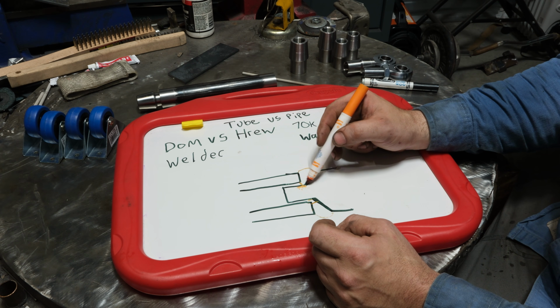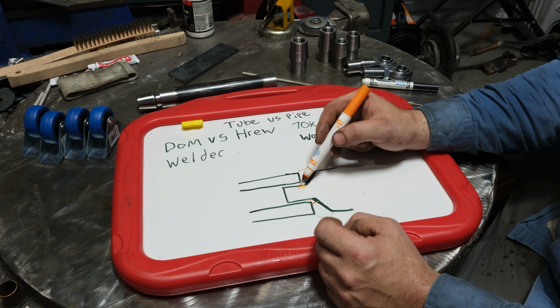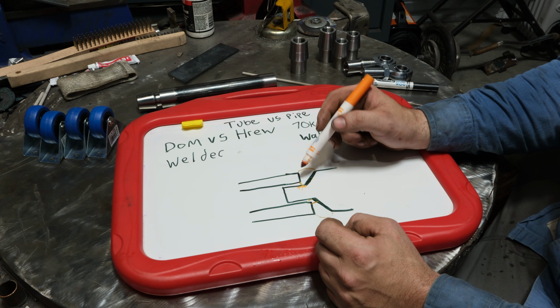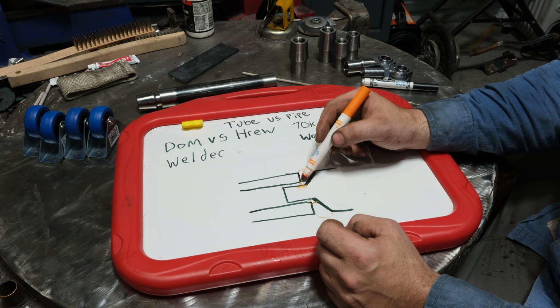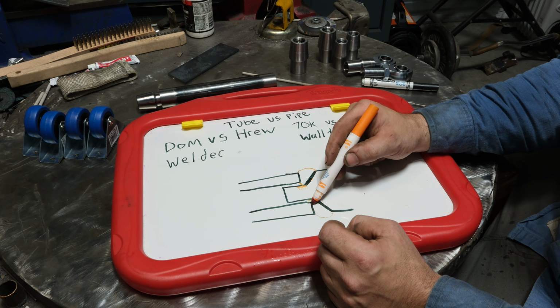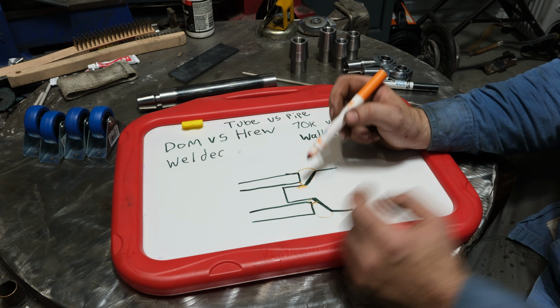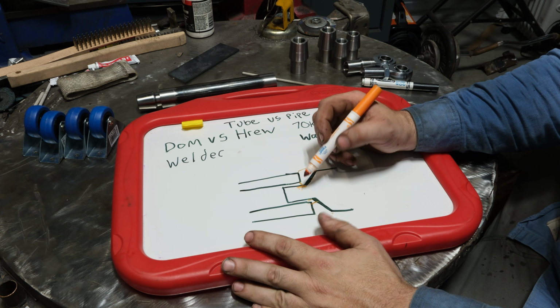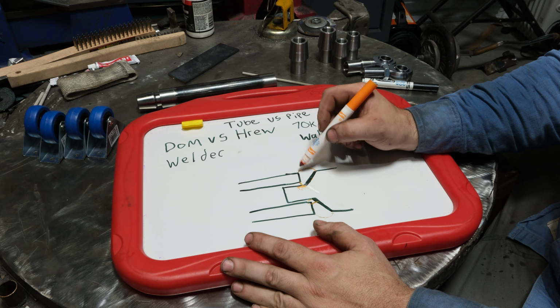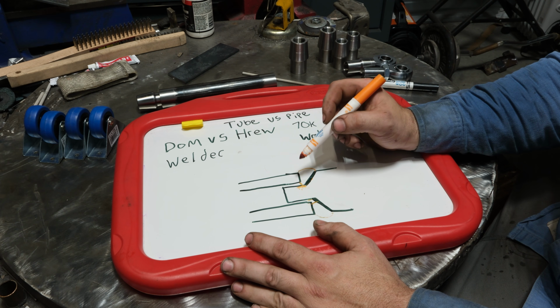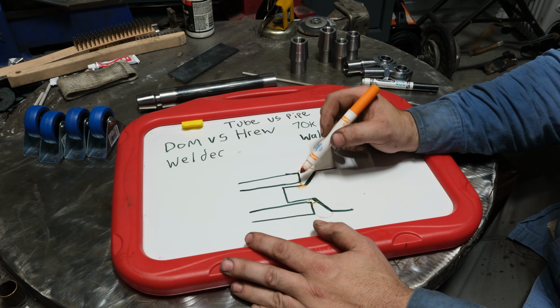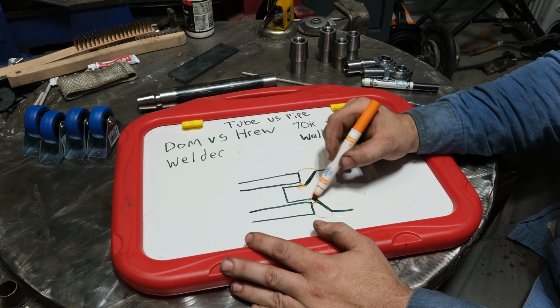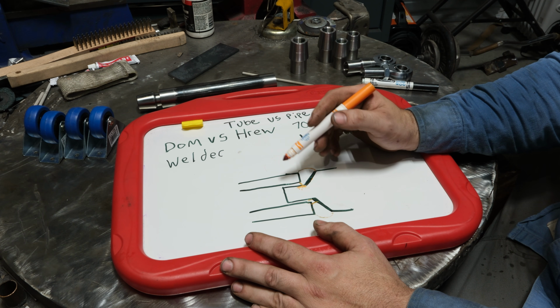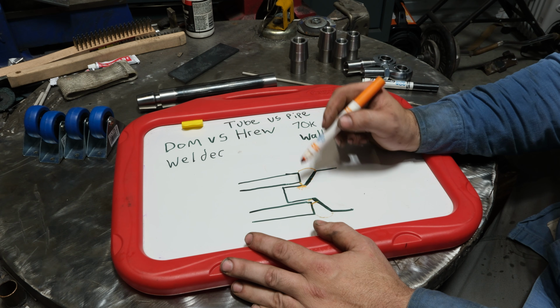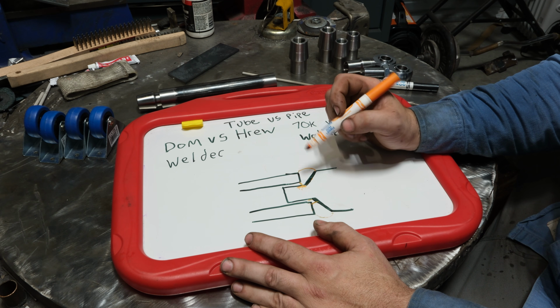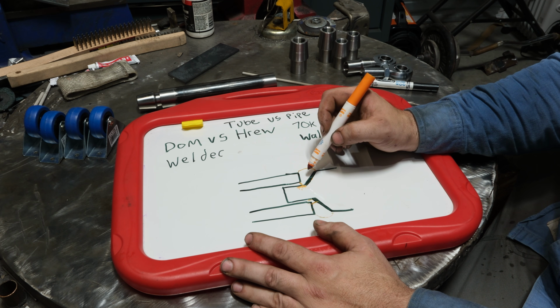What I've found is when you cram it tight and run it super hot with TIG, it's more common to have this than MIG, because MIG doesn't have very much penetration, so it almost always will bridge over just like this, the way you want it. Now you got to remember, this whole thing is welded all the way around the tube. The probability of it breaking, even with a lack of fusion in this area, is almost none, especially if you were running settings that were appropriate for this material. So that's all things to consider.